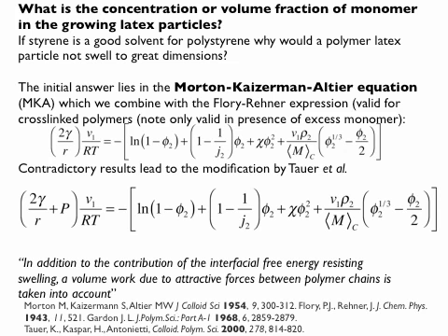As a matter of fact, in this particular case, if you would look at polystyrene and styrene, without any cross-link density, the right-hand side effectively, if that was only there and you wouldn't have a particle, you could infinitely dilute. The left-hand side would restrict that. So the important restriction in that particular case would be the increase in interfacial energy, because the radius of the particle would go up.